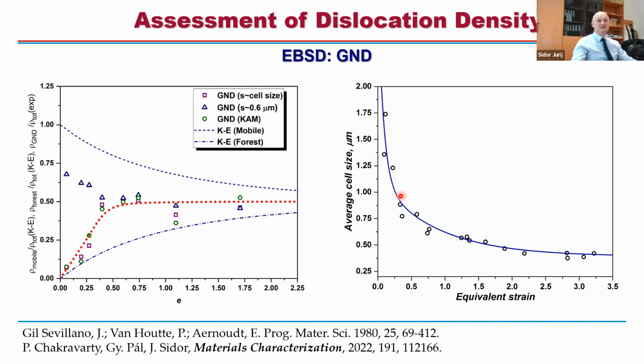subcells with strains. For instance, in aluminum alloys, I took this data, and then I drew a line, and basically now I put all the coefficients into this equation, which I derived for this curve, right? And I can immediately calculate the cell size. Once I know the cell size for various strains, based on this, I can define the step size for my measurement.